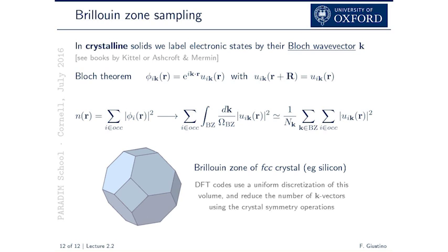That's the way we represent the Brillouin zone in a discrete way, okay? That is not important if you do molecules, but it's very important if you do a crystal, okay? Because you need to take into account the Bloch theorem when you do these calculations. And also this is a convergence parameter, so the total energy will depend on how many points you put in there. So you need to make sure that you have enough that your energy is stable, is not changing anymore.